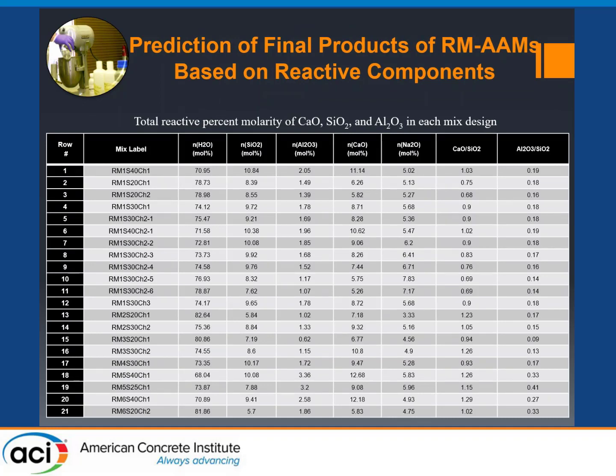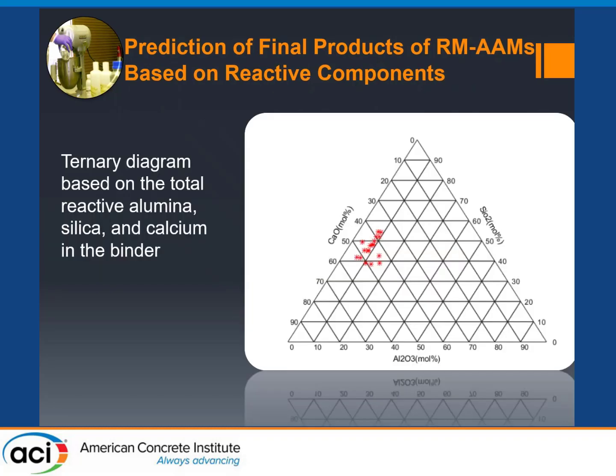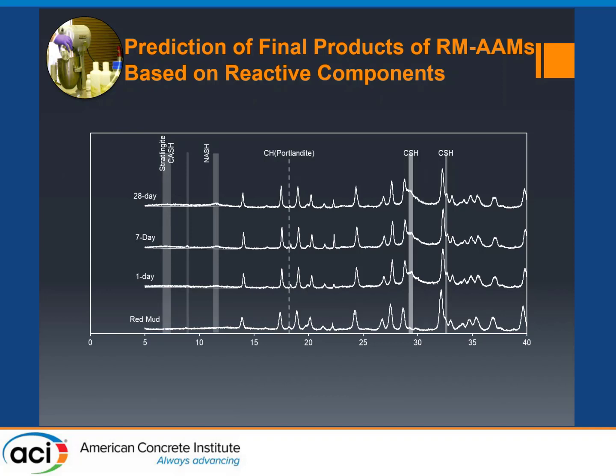We're trying to predict the final hydration product. For this case, it's red mud AAM, based on this reactive component. So we're trying to predict what kind of hydration product using this ternary diagram, and also XRD and XRF. And we're trying to verify the hydration product using XRD.